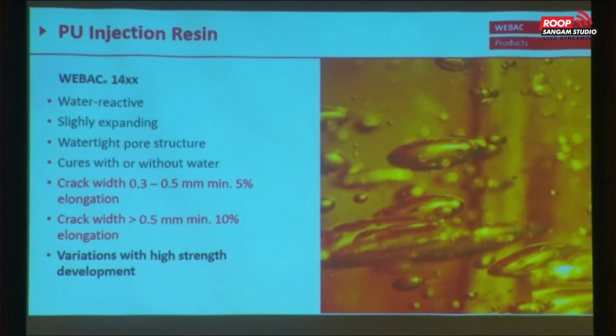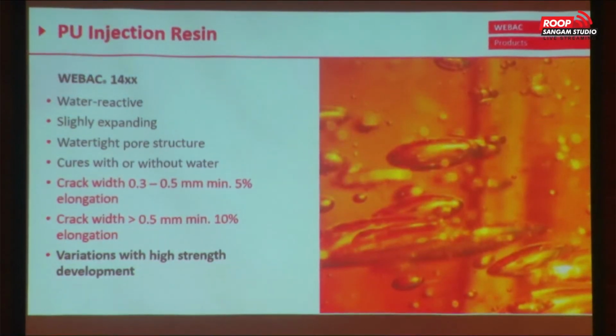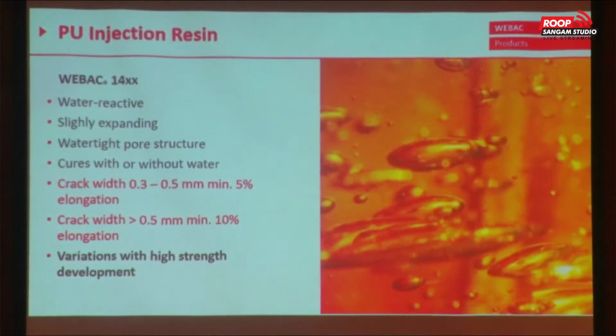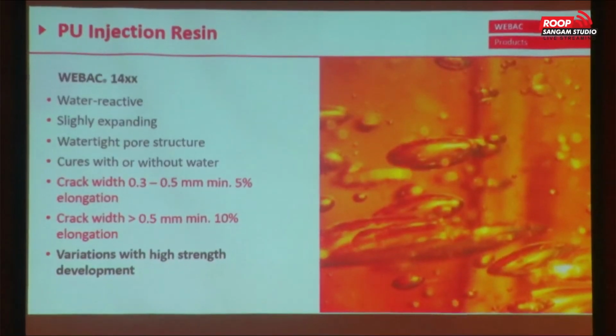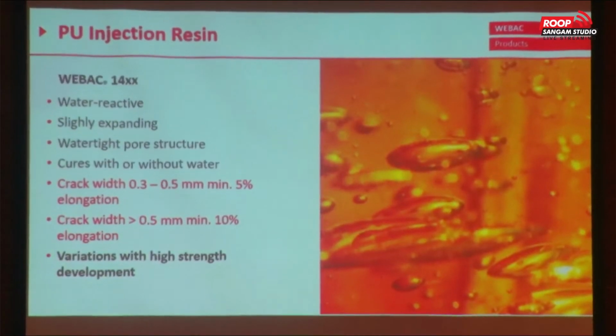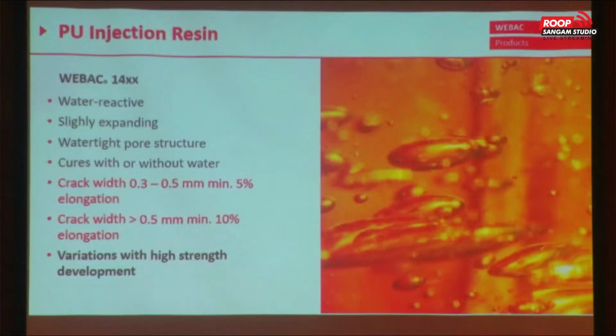Then we come to the PU injection resins, which are for permanent sealing. It's mentioned in our 14er row. They are also water reactive, slightly expanding, and cure with or without water. They have a good elongation. You see, for crack widths between 0.3 and 0.5 millimeters, we have an elongation of 5%. Wider than 0.5 millimeters, we have an elongation of 10%. Think about it: you have this fine crack and you have that elongation. That is totally enough to cover a lot of movements.